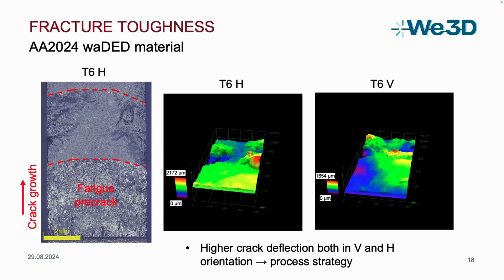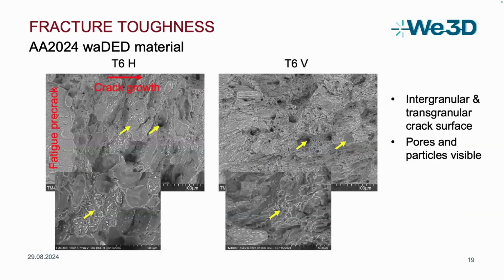The evaluation of the crack deflection also looks a bit different here because it's much higher. So we have about 2 millimeters in the horizontal sample and 1.5 millimeters in the vertical sample, which basically comes from the process strategy with the weaving movement. In the SEM, we can also see intergranular and transgranular regions, but we can furthermore see some defects like pores in the material and also some particles at the grain boundaries.